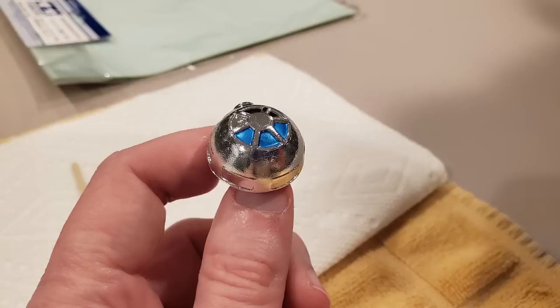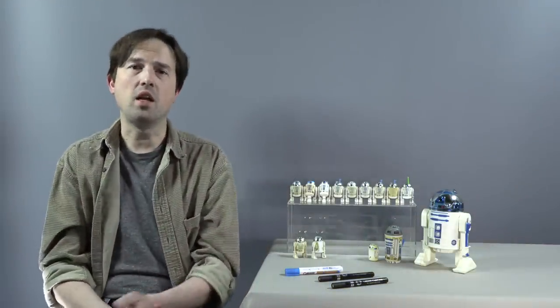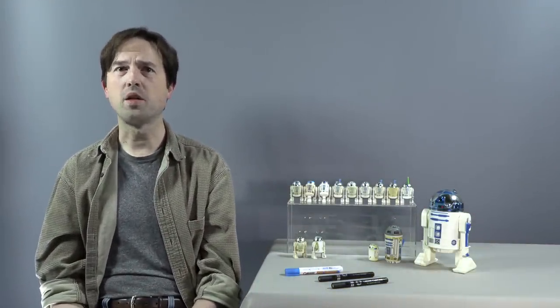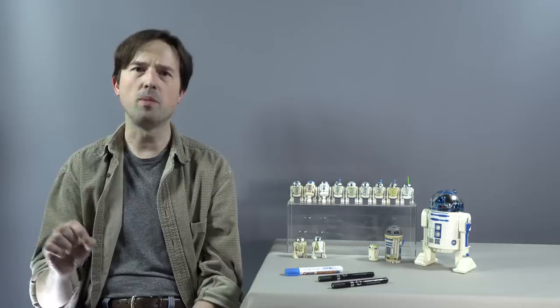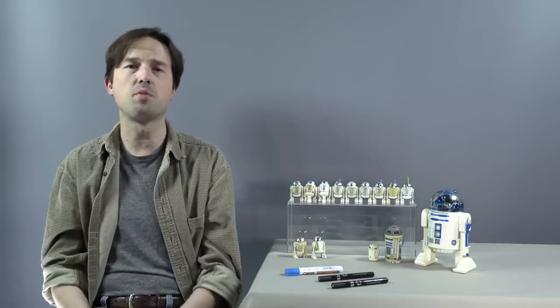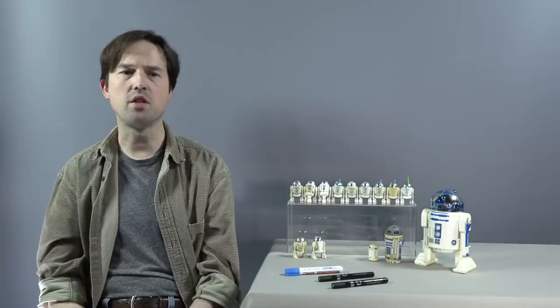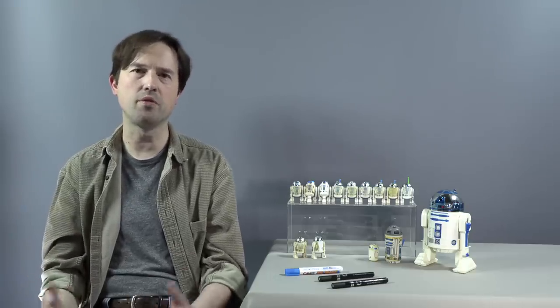He asked if I'd tried using the Molotow chrome pens. I said I opted not to because I went with vac-metallizing. He said it's possible to go over any remaining chrome, like he's done on some projects, while filling in other areas. The only thing is you've got to let it cure for about a month.